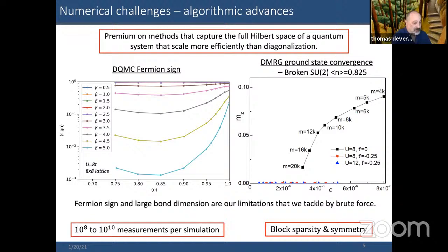And so this has always been the case, but now, of course, we can increase the amount of measurements that we do. Everything that I'm going to be showing you is based on 10^8 or 10^10 measurements per simulation to be able to deal with the small value of the sign. And it's, of course, a well-known problem that the sign is worst exactly where you want to put your efforts, right around what would be nominally optimal doping or 85% filling. On the other side, DMRG is unbiased and asymptotically exact as well, but has a limitation of trying to extend to dimensions greater than one. Both of these techniques suffer from the exponential complexity that one has in this problem.